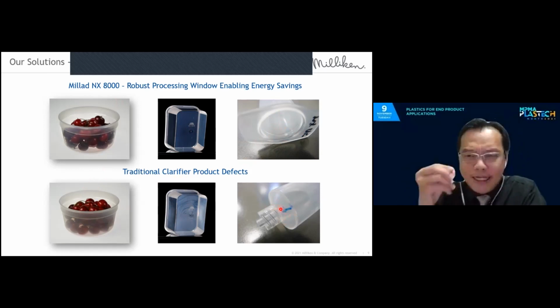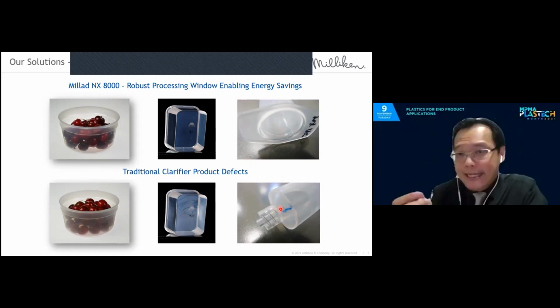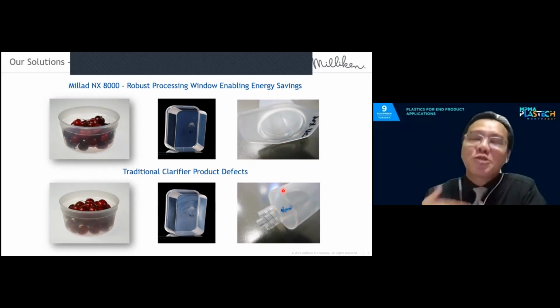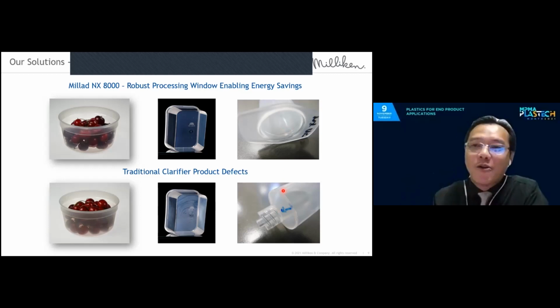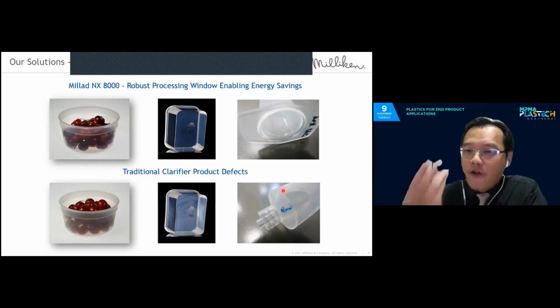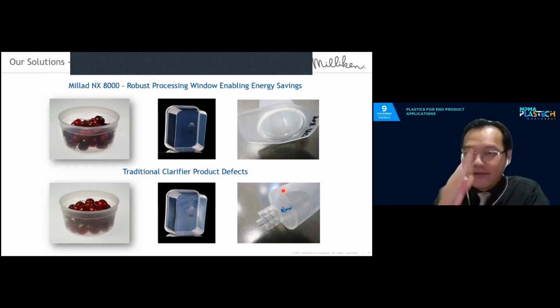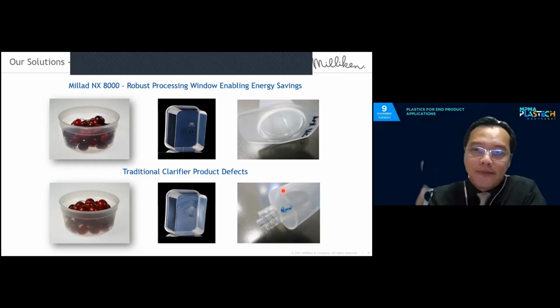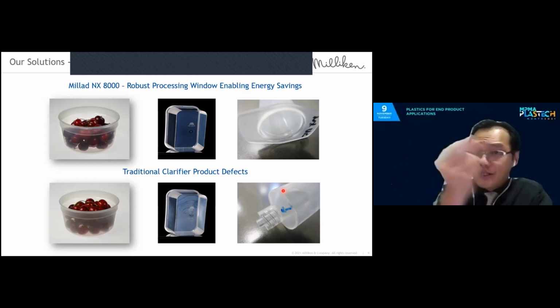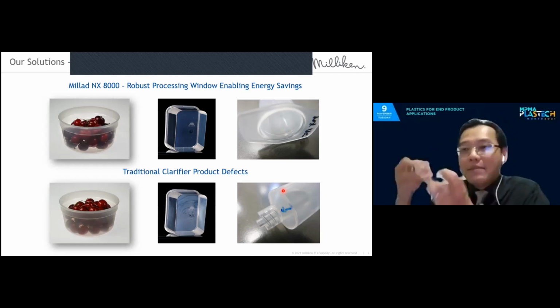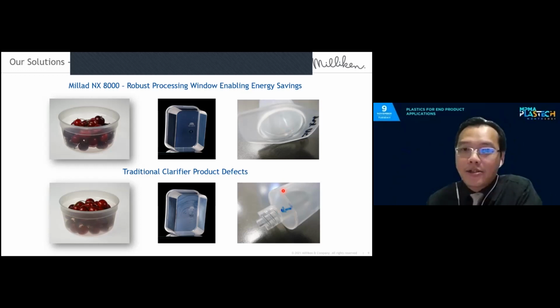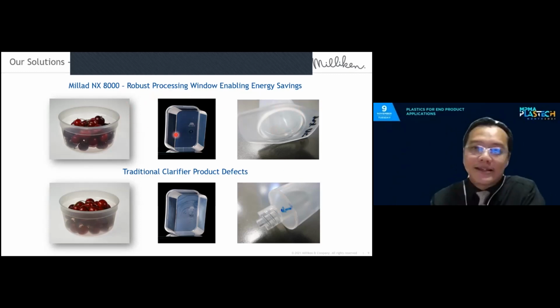and especially voids in certain parts of the plastics. So voids are, it's not an air bubble trap, but it looks like that, right? And especially now, a very close to home application of syringes in this COVID world, vaccination, voids in a syringe body is a very no-no, right? To let the nurses and the doctors have full confidence that they are injecting it properly. You do not want them to mix up really defects in the syringe barrel with really air bubbles trapped in this medicine they are injecting. So really, not just energy savings, but really a trouble-free, robust processing window, less defect when using NX8000.